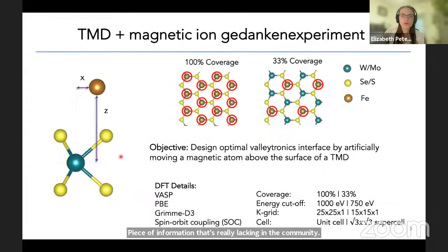So what I've done is performed a bit of a Gedanken experiment where I take a monolayer TMD and I take an iron atom and place it at arbitrary locations above the TMD. I consider both 100% coverage to see what's the absolute maximum valley splitting that we could achieve, where coverage refers to how many iron atoms there are per transition metal, tungsten or molybdenum. And I look at 33% coverage, which is a bit more realistic for an actual substrate. I'm performing these calculations using VASP with PBE with Grimme D3 van der Waals corrections and spin orbit coupling.